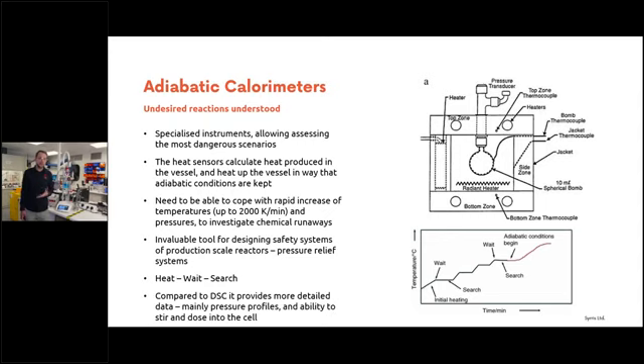And if you look at the mode of operation, the typical mode of operation of an adiabatic calorimeter is heat, wait, and search. So if you look at a thermogram, it works in a staircase kind of way, where it will heat up by a given amount, wait for a given time at isothermal conditions, and then search for any changes in the temperature. If it doesn't fit in the margin, it will continue to the next step until it can detect some thermal event happening in the crucible. Then it will switch to adiabatic mode and record the whole heat release during the decomposition in the vessel.